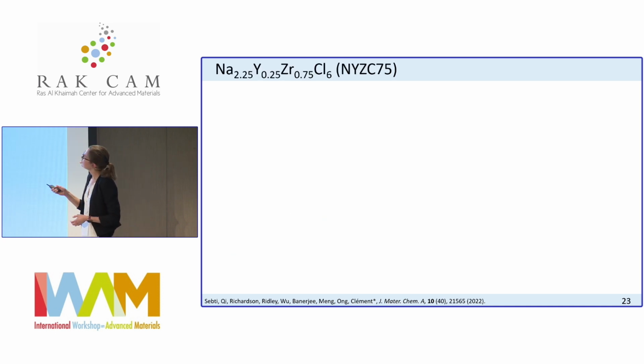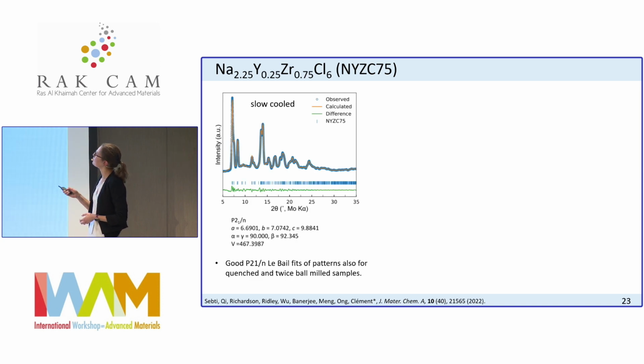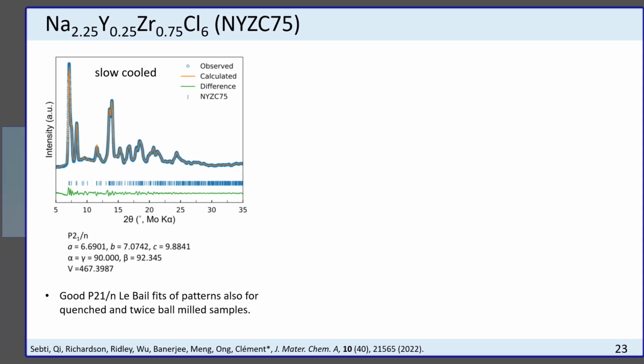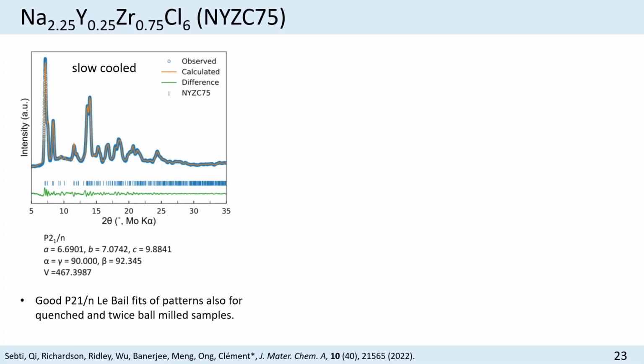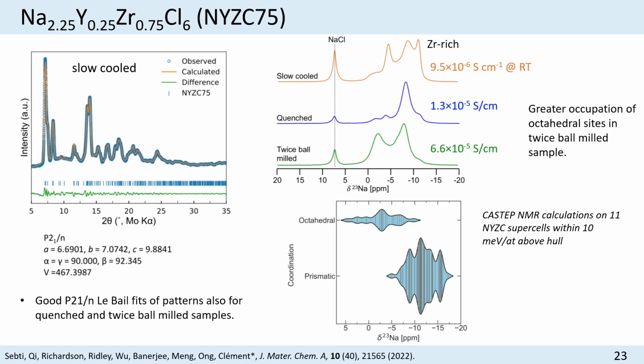So now if we move to the more interesting zirconium-doped system that we found was optimal for conductivity in our previous study. In this material, we actually form the P21 over N monoclinic structure, whether we slow cool, whether we quench, or whether we ball mill it twice. If you look at the NMR data, what you're finding here is we do have an evolution of the distribution of sodium in the different sites in the structure.